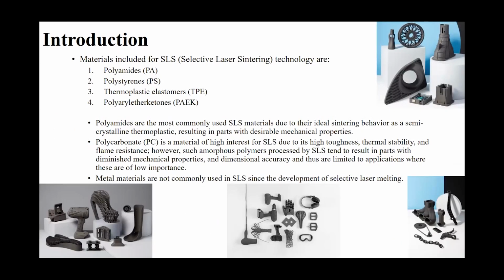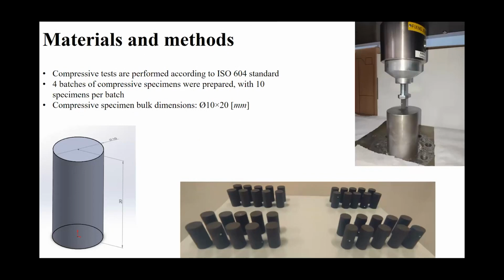Materials used in SLS technology are polyamides, polystyrenes, thermoplastic elastomers, and polyaryletherketones (PAEK). In this research, one type of specimen is used for mechanical characteristics according to the dedicated standard ISO 604. Compressive specimens are 10 by 20 millimeters in bulk. Compressive specimens were prepared in 4 batches with 10 specimens per batch. Batches differ in printing orientation and printing location. In this case, printing orientations are vertical and horizontal, and the printing location is on the edge and in the middle of the powder bed.